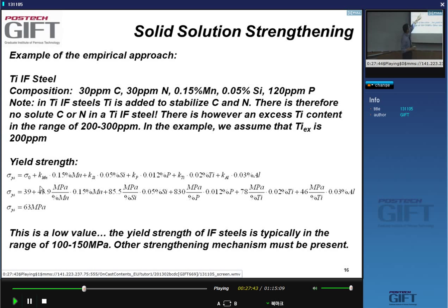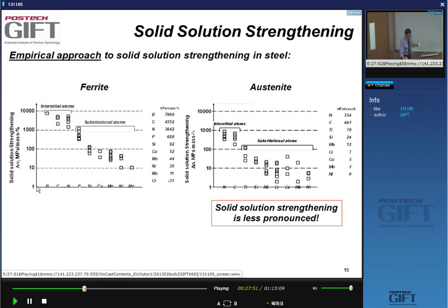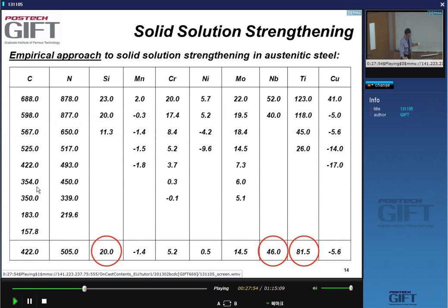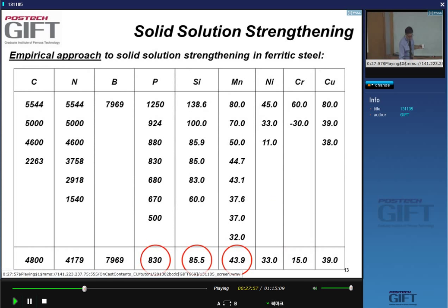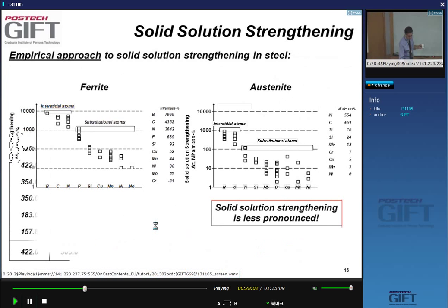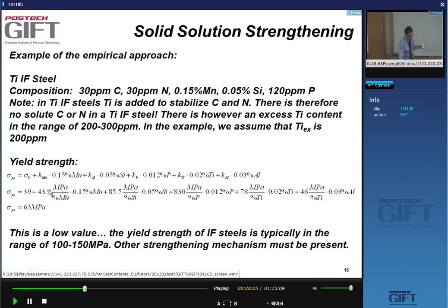the strengthening effect. So for manganese, I had in my table here. Let's go back here. Right, so you have here 43.9, that's this median value. So here 43, I multiply with the weight percent of manganese. I do the same for silicon, phosphorus, titanium, and aluminum in my composition. I sum this all up, 63. Now 63 is very low, yeah? 63 is a very low value for the yield strength,